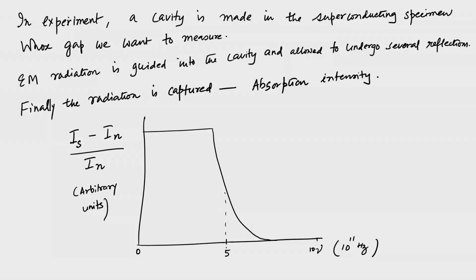So, basically what it means is that beyond this frequency, 5 into 10 to the power 11 hertz, there is no difference between the superconducting state absorption and the normal state absorption. Now, the question is, why does it happen? And of course, if you go to larger frequencies, the difference between them remains 0. So, this abrupt drop of the absorption spectrum results from the quantum energy of the radiation becoming equal to the binding energy of the pair, or the energy gap that we talk about, and then the Cooper pairs are dissociated.